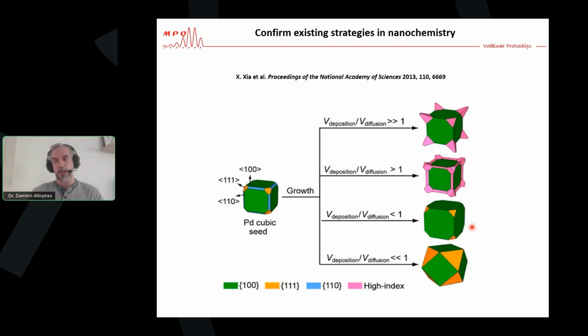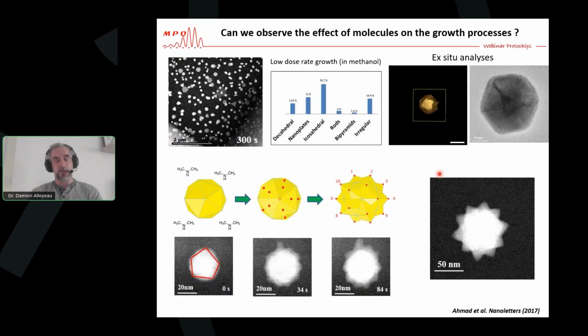Now, another way to play with these faceting mechanisms is obviously to play with the functionalization. And at that time, we wanted to answer the question: can we observe the effect of molecules on the growth process? So in this experiment, we started from the low dose rate experiment, where we grow well-faceted nanoparticles, and we have studied the shape distribution of those particles. And you see most of them are decahedral nanoplates, icosahedral nanoparticles. You have also some rods and some irregular shapes, but most of the nanoparticles are decahedral and icosahedral nanoparticles. You see here the tomography experiment on the high resolution image of those icosahedral nanoparticles.